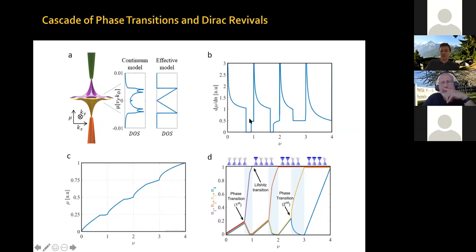this is an actual calculation of the inverse compressibility, the mu dn, as a function of filling factor, and you can see that you have this Dirac behavior, then the first phase transition occurs here, which leads then to another Dirac revival. Same thing happens here. Depending on whether you have a Lifshitz transition, a first order or a second order phase transition, the details can vary, but you can see that those peaks, those resets, happen at each integer filling factor. So you're saying it's the Coulomb interaction that drives this phase transition? Yes, yes. Okay, I see.